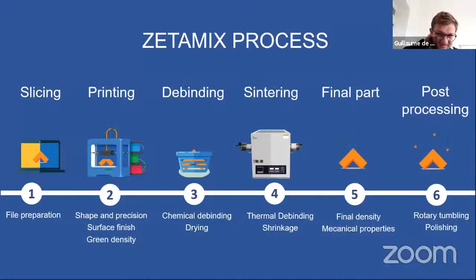And then how do you use these filaments? It's something which has started to be quite well known, mainly a three-part process, which are the three parts in the middle: printing, debinding, and sintering. So when you print the part, you actually print a mix of thermoplastic binders and powder. And then in steps 3 and 4, you're going to eliminate the binder and make a very high temperature heat treatment to densify the part, to give it its strength. Obviously, before that, you need to prepare the file for printing, and after that, you can have some post-processing. We'll go into the details of all of this process, but it's good to see the full picture before starting to get really in the details.